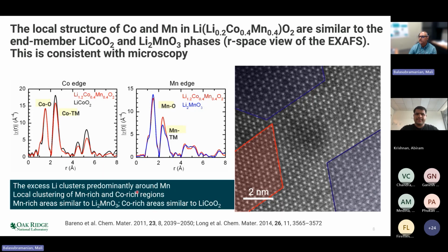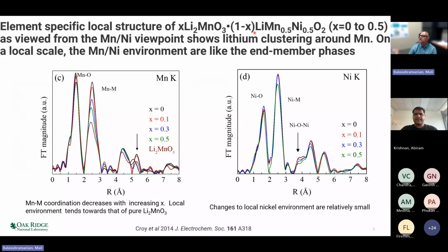Now, similar things can be seen in other systems. For example, here is a system which has manganese and nickel, and you can see that as the value of X increases, that is, you are making it more towards the Li2MnO3 side, the XAFS, the manganese XAFS, starts looking more like Li2MnO3, and this coordination here, which comes from the manganese metal shell, decreases. So the local environment of manganese is looking more like pure Li2MnO3, and the excess lithium is again clustered around the manganese.